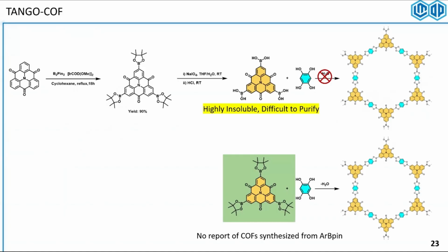And what I noticed was that when we had these B-pin groups, both from the synthetic perspective and for the solubility and easy purification, they were very easy to work with. But as soon as I took the B-pin off to make the bare boronic acid to make the COF, it just turned into a highly insoluble, impure mess that we could not form anything with.